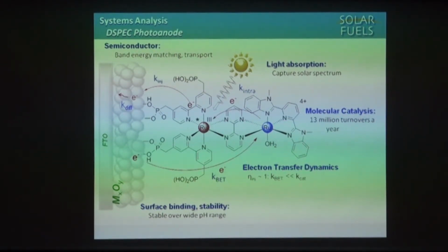Why? You've got to get the right band energies for injection and charge transport. You need to be able to do surface binding. If you have phosphonate derivatives of almost anything, at least in acid solution, they form relatively stable chemical bonds to the surface. I'll come back to this at the end, how to make this better. Light absorption. You need to capture as much of the solar spectrum as you can so your device can be efficient. Remember, we've got to have efficient devices that are inexpensive.